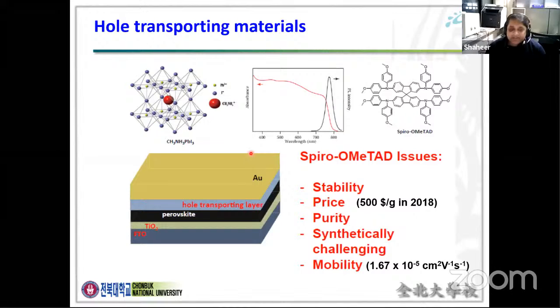So the reference device that I mentioned before uses the HTM material spiro-OMeTAD, which has the biggest problem of stability, and another problem is the cost. So far, there are many chemical companies producing this kind of spiro-OMeTAD HTM material, but the cost is still very high, like $500 per gram. So in order to avoid these kinds of issues,